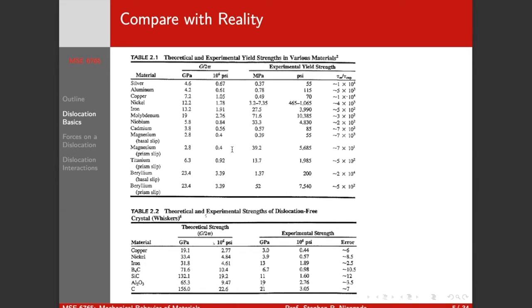So another piece of evidence that came up about the same time, people made really thin whiskers. We would call them kind of nanowires today. And when these whiskers were really well annealed, their experimental strengths approached their theoretical strengths. So this led people to speculate that there's some kind of defect in the crystal that is facilitating the easy plastic flow of these crystals.